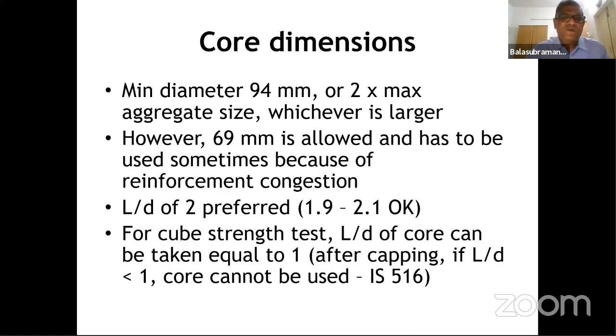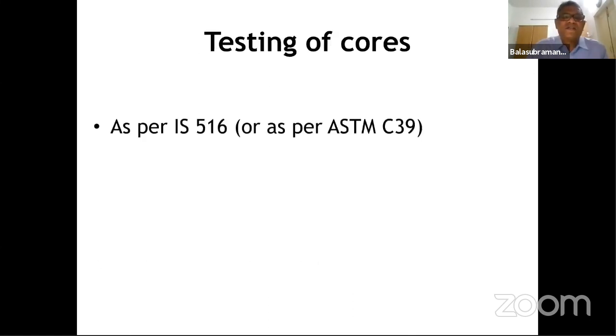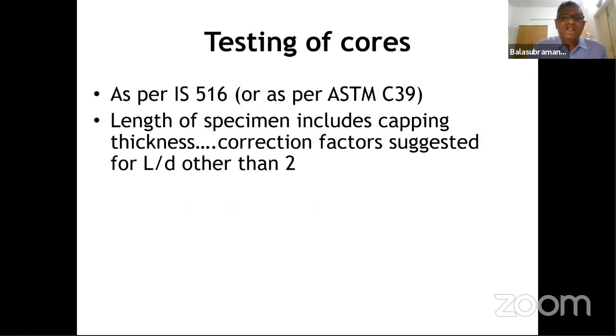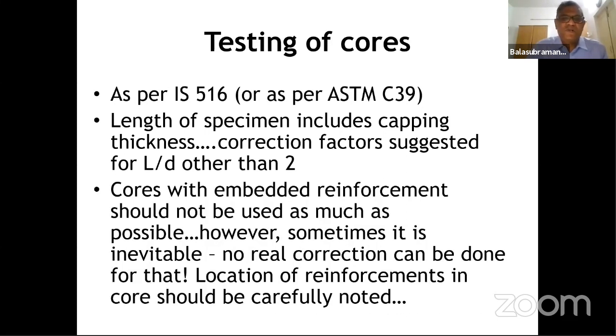And generally L/D of 2 is preferred. Now the new code has given you correction factors for L/D which are not exactly 2. And for any L/D less than 1, we should not test the core, because it will not give a proper result. And testing of the core is as per IS 516. L/D should be 2, try to make it as close as possible to 2. And the core with embedded reinforcement should be avoided as much as possible.